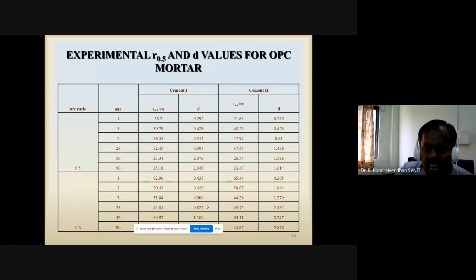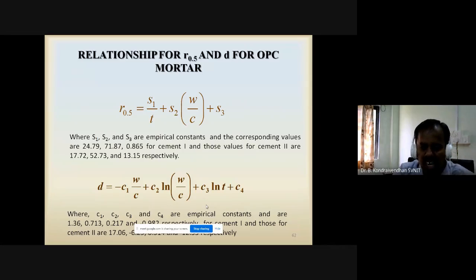Okay. So then we have extended this work to cement sand mortar also. But here there is one complication, because once we introduce the sand particle, due to the wall effect and loosening effect of the particle, it induces some ITZ porosity. Actually, there is no idea available so far how to quantify the ITZ porosity. Even Powers' model is not incorporating the ITZ porosity. That's why it is not possible to do theoretical modeling, so we have done only empirical modeling.